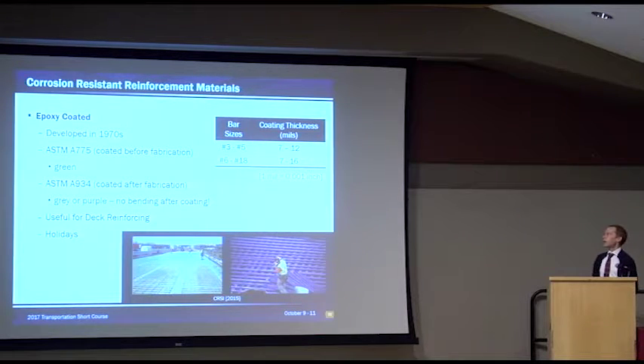What I'll point out, the coating thickness is 7 to 12 mils, mils being thousandths of an inch. If you've seen it in the field, I've always seen it green. We have two different ASTMs we can specify it by. If you see green epoxy coated rebar, that means it was done by one process, a process that allows it to be fabricated after it's coated. If you see somebody bending a green bar, it's okay. Purple epoxy coated rebar is a different kind of coating, and after it's coated, it can't be fabricated. So if somebody's bending a purple bar, or a gray one, same thing, that's a bad thing.